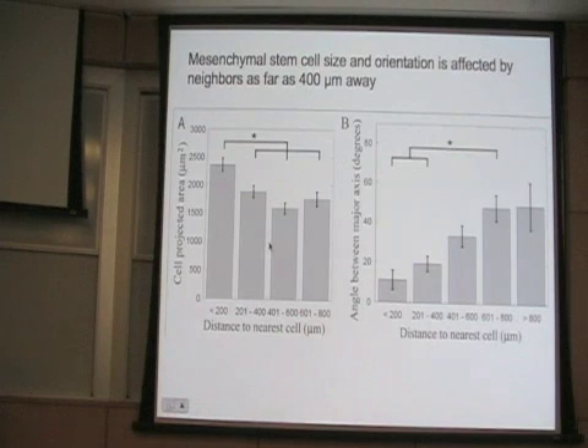Here's an example of how far away cells can sense each other's presence. So these are still very sparse populations of cells. They've never come together and touched each other. They're not laying down the chemical path that we know about. They're just feeling each other mechanically. And you can tell that they felt each other mechanically because if you look at the spread area of the cell that is within 200 microns of its nearest neighbor, those cells are bigger than cells that are 400, 500 microns away. So they don't have to touch a cell. They can just be near a cell and become bigger, presumably because they felt some stiffness.